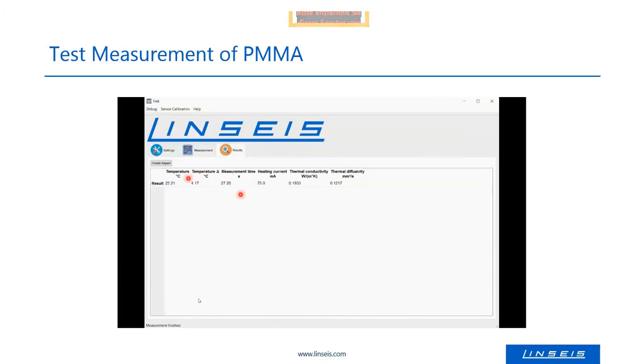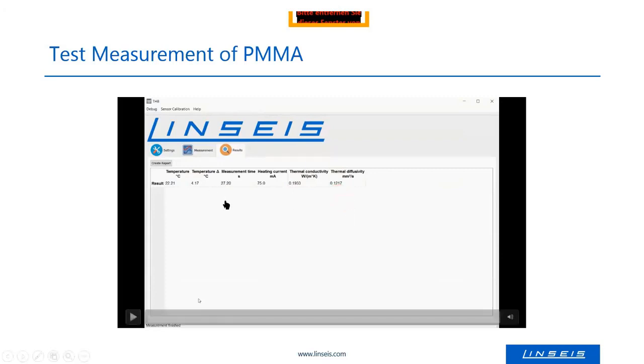And that's it. And now you see, after 27 seconds, you have the result: 0.1933 for the thermal conductivity, watt per meter Kelvin, and for the thermal diffusivity, it's 0.1217. And the temperature here, it's also measured with the sensor. So the measurement started at 22.2 degrees Celsius, and the temperature increase on the sensor surface during the measurement was 4.17 Kelvin.